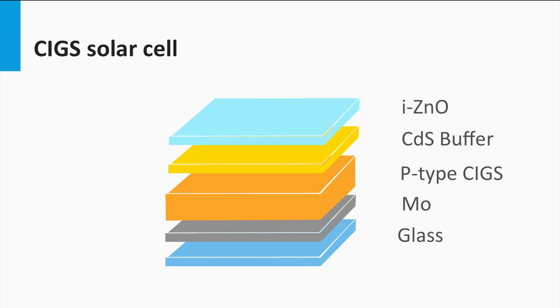The n-type region is extended with an n-type TCO. First an intrinsic zinc oxide is placed, followed by an aluminum doped zinc oxide. The aluminum doping makes the zinc oxide n-type.